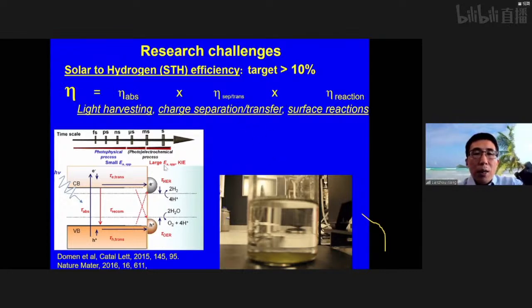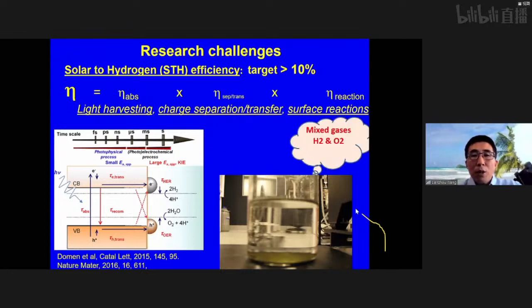the current technology. But if you look at the key processes of the photocatalytic reaction, you can see it covers a very broad time scale, from the light absorption to the surface reaction, and that also generates a lot of opportunities for the charge carriers to be lost, to be recombined, and not get efficient surface reactions to happen. And in the powder form, we also have a challenge: if you have the photocatalyst in suspension, you have hydrogen and oxygen produced as a mixture, and it's a two-half reaction. And this is pretty dangerous as well. We also need a separating approach.